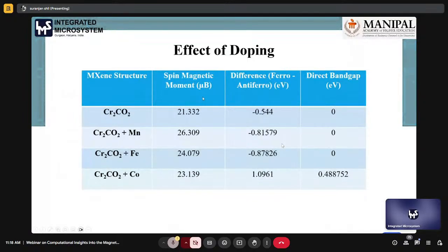And now we try to understand the magnetic behaviors with the doping. If you see in chromium carbide, without doping, we got the energy gap between the ferromagnetic and anti-ferromagnetic configuration of minus 0.544, which is ferromagnetic, and the spin magnetic moment is around 21. And if we dope with manganese, we see that the magnetic moment increases. It's 21 to 26, it increases.